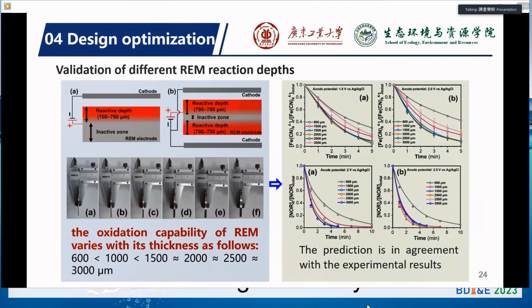Also, our findings can help us to optimize the design of the electrodes. That is, to find the most economic thickness of electrodes. We have prepared a few electrodes with thicknesses from 600 micrometer to 3000 micrometer, according to the model and the visualization results. The reaction depth is around 700 to 750 micrometer, and because it has a double side, so the total reaction depth is